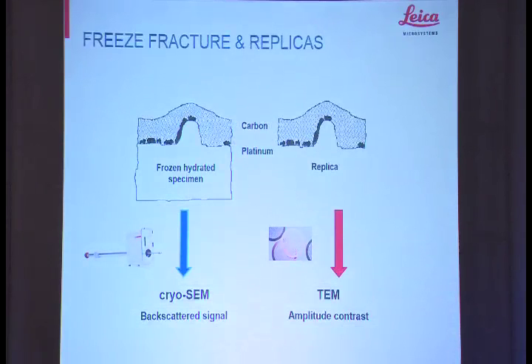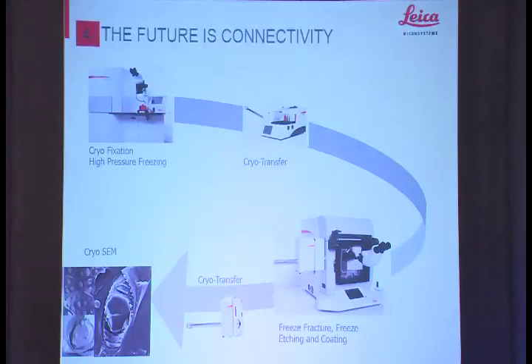And we can use our frozen sample in two ways. We can make a replica from the frozen sample, remove the sample itself and just leave the carbon and metal coating and transfer that to the TEM. Or, as mentioned, we can take the frozen hydrated sample itself and transfer it to the Cryo SEM.